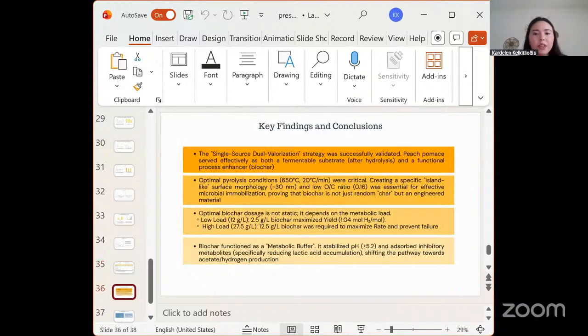In conclusion, we validated the single-source dual valorization strategy from peach pomace, proved that biochar must be engineered with specific heating rates for optimal morphology. Confirmed biochar acts as a metabolic buffer by maintaining pH above 5.2 and absorbing lactic acid.